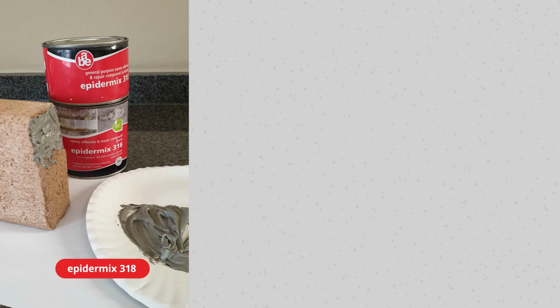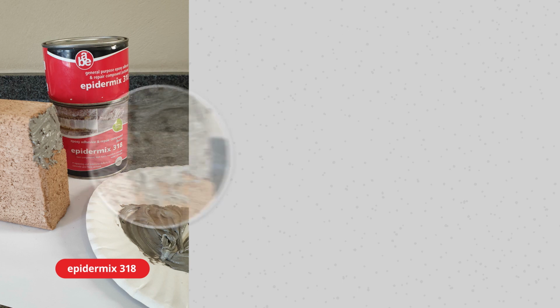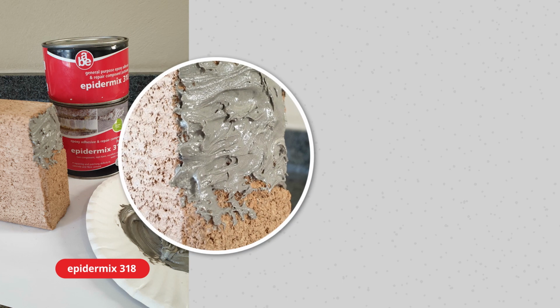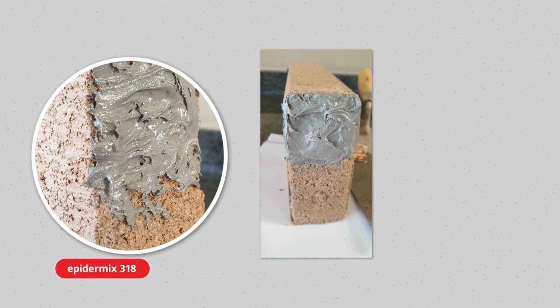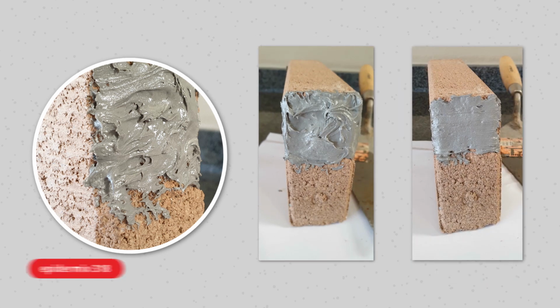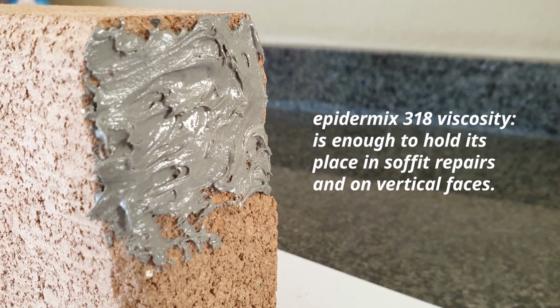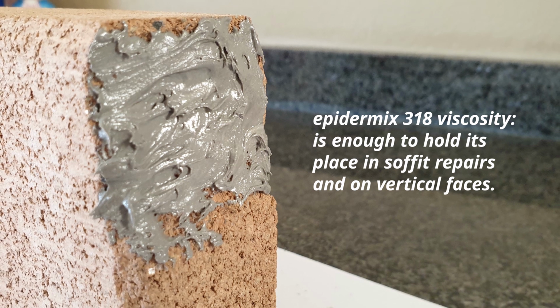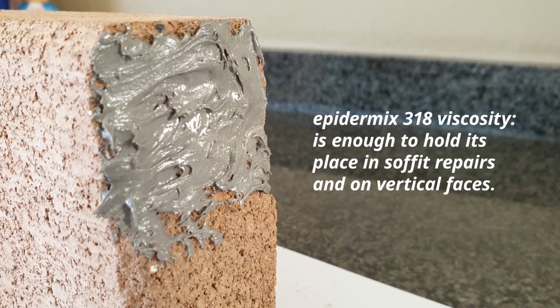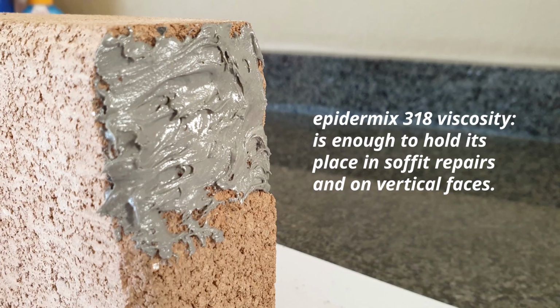Mixed Epidermix 318 should be pressed into place in the repair area using a small amount first to wet out the surface and then building up the required thickness. The viscosity of Epidermix 318 is enough to hold its place in soffit repairs and on vertical faces.